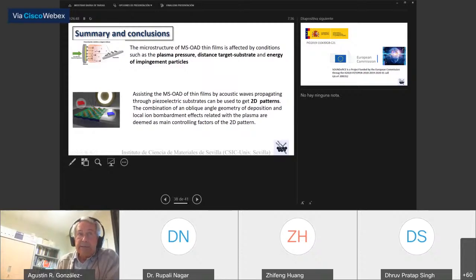And on the other hand, if we use acoustic wave to activate the deposition process in an oblique angle deposition configuration, it is possible to pattern the deposition process and to get patterns which can be tailored, changing the deposition condition, type of acoustic wave. So there is plenty of work and field to work with in order to have a patterning during the deposition process.